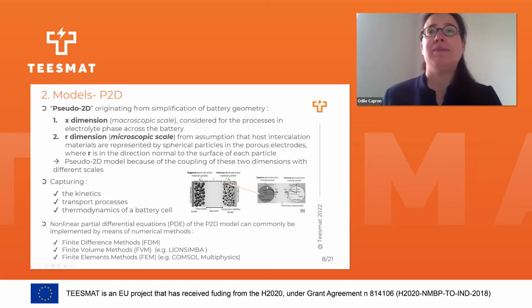As you can see here on the scheme, that's what I mentioned. The X dimension is along the thickness, when we consider a layer of positive, negative, and in between the separator and the collectors, whereas the R dimension is at the level of the active material particles. By coupling these two dimensions, we call it a pseudo two-dimensional model. They have different scales, and therefore it's pseudo two-dimensional.